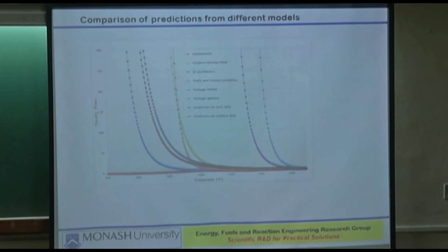And then the important thing is, once you find that you can measure it, then you get the data, and the question is how you will relate it to the chemistry of the liquid, which unfortunately has changed because it has stayed at that temperature for a long period of time. So mineral transformations have also taken place. That has to be captured somehow.